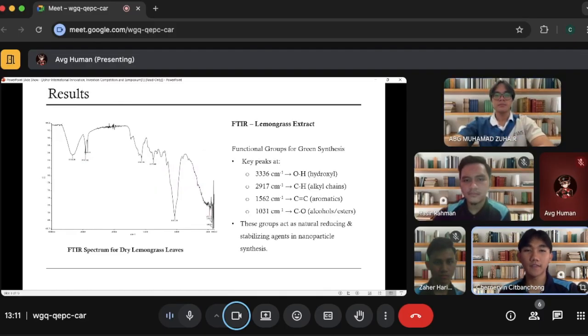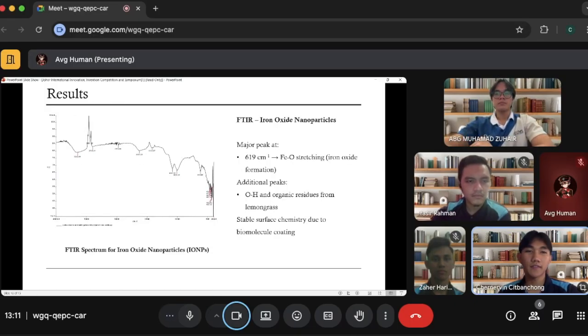Now let's move to results and discussion. We will first start with the characterization of lemongrass leaf extract using Fourier transform infrared spectroscopy (FTIR). FTIR analysis of lemongrass extract shows peaks linked to hydroxyl, alkyl, aromatic, and ester groups. These functional groups are crucial. They act as a natural reducing and stabilizing agent in nanoparticle formation. As for the biosynthesized iron oxide nanoparticles, the peak at 619 reciprocal centimeter confirmed the formation of the iron-oxygen bond, indicating successful nanoparticle creation. Several peaks similar to the FTIR result of lemongrass leaf extract may be due to organic residue from the plant, suggesting that the nanoparticles are stabilized by biomolecules of lemongrass leaf capping them.